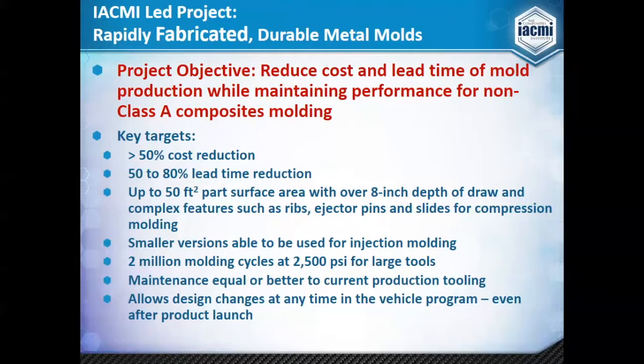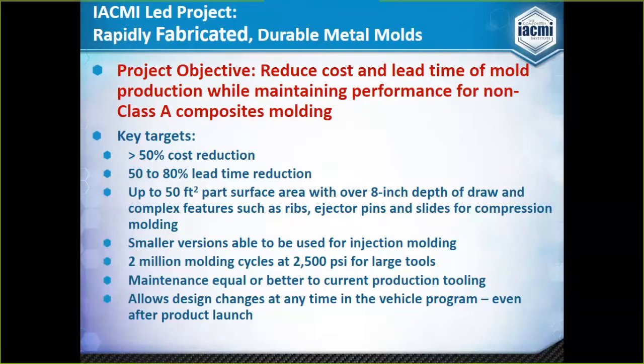Durability is something we're really going after. So we're not talking about trying to do this with mild carbon steel, but with tool steels. How do we do this with tool steel to build these up and get that kind of durability that you need for the surface, up to say 2 million molding cycles at 2,500 psi. So this is the goal of this project.